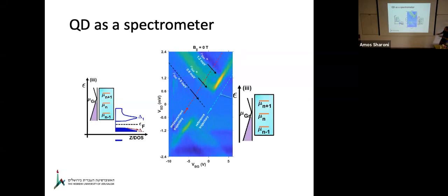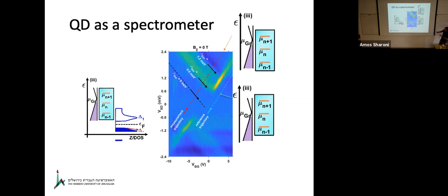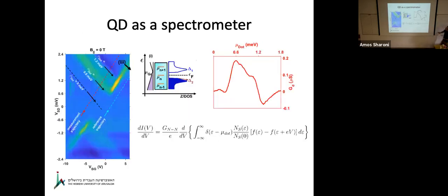And the reason you can see that is that along this trajectory, the dot is in the Coulomb blockaded region, it is forbidden. And along this trajectory, the dot is parallel to the source onset, which I defined before. That means you can tune the dot by sweeping it versus the energy of the superconductor, and therefore the transport along this trajectory is actually a measure of the superconductor density of states. So what we can tell now is that we measure the transport through the dot, and we see that there are two peaks. Now I told you before that niobium diselenide is a two-band superconductor.